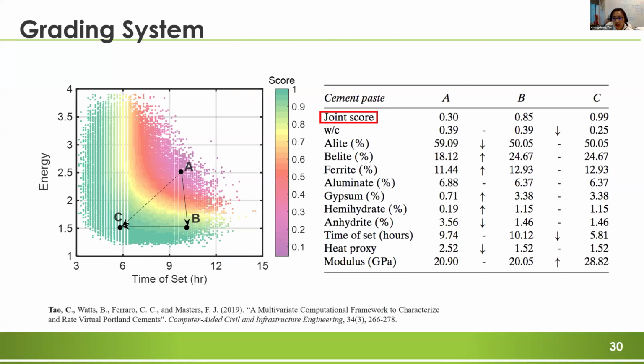According to the optimization result, I also developed a grading system ranging from 0 to 1 to evaluate the performance of the cement materials by considering multiple factors such as material property, energy consumption, and sustainability. So here is an example. From the figure on the left, cement A has a relatively low score. We define it as 0.3, because it has high setting time and high energy consumption. If we modify cement A by reducing the Alite and increasing the Belite to produce cement B, we can see the score is increased to 0.85 because the energy consumption is reduced.